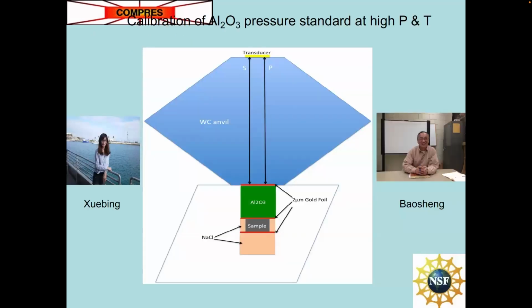The next slide. Sorry, I'm a little bit out of line because I can't see the whole slides. One of our graduate students, Xuebing Wang, did a very clever thing in the laboratory of Baosheng Li a few years ago. She decided to use polycrystalline alumina and measure its wave velocities as a function of pressure as a sensor. So we had within the sample chamber this octahedral arrangement, we had a pressure standard so that the transducer would transmit the acoustic wave through the anvil into the acoustic buffer rod, the alumina in and out of the sample. And so we had a more direct measurement of the pressure within the sample chamber.